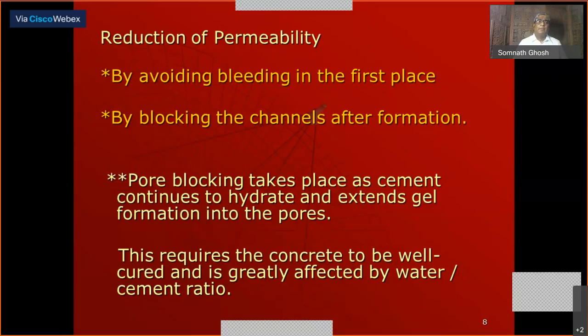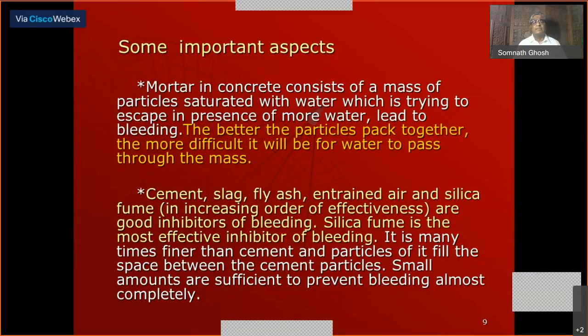Now you see, mortar in concrete consists of a mass of particles saturated with water, which is trying to escape in the presence of more water, leading to bleeding. You all know, the better the particles are packed together, the more difficult it will be for the water to pass through this mass. This is common sense. And cement, slag, fly ash, entrained air, silica fume, I'm telling you in increasing order of effectiveness, are good inhibitors of bleeding. Why am I talking about bleeding? Because bleeding is very, very important in the case of high performance concrete. Silica fume is the most effective inhibitor.